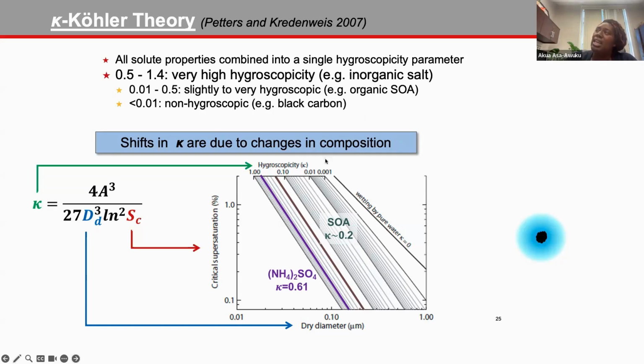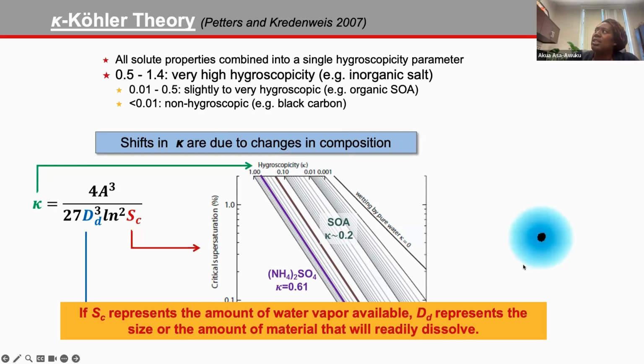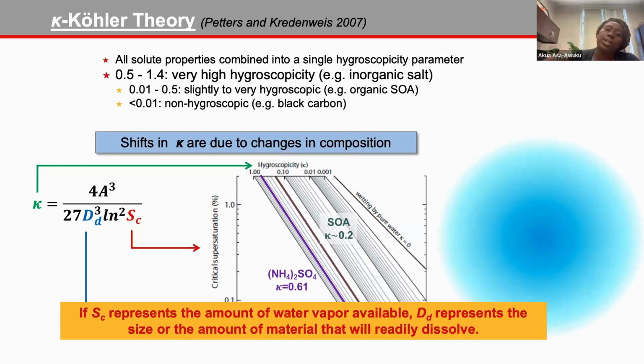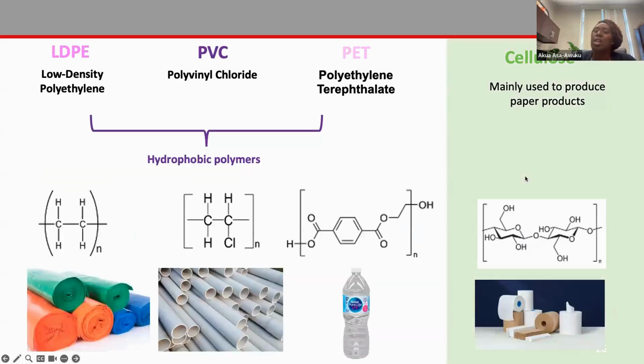Now, the key part about this, and I'll get to this later as well, is that kappa-Köhler theory assumes that the solute, the aerosol itself, contributes essentially its molar volume to the dissolution of the droplet, which actually activates more droplet growth. I'll come back to that because we're talking about plastics, and that may not necessarily be the case. So for the study, we're interested in the droplet activation of these 3 plastics. In addition, we also threw in cellulose.